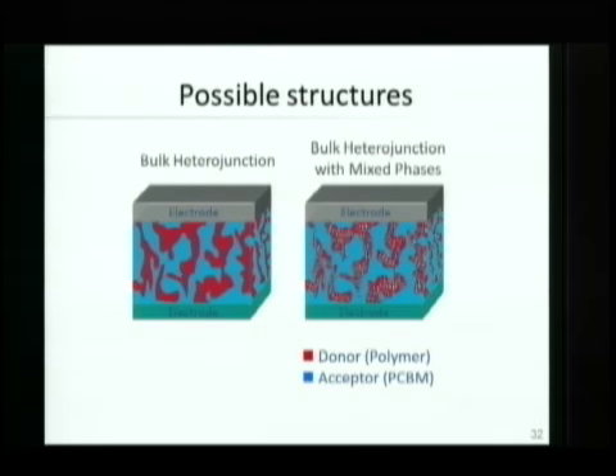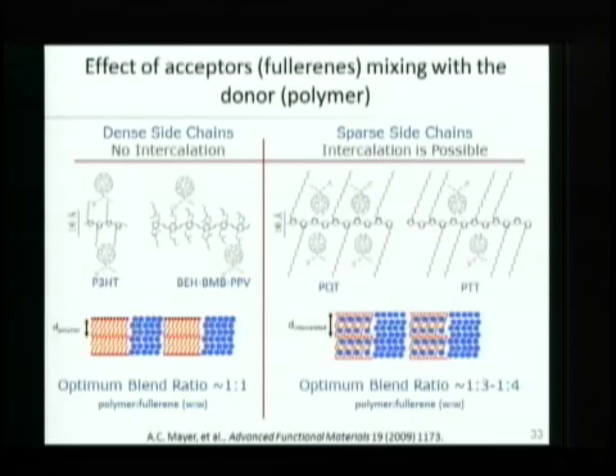And we need to know things like, do you have pure regions of donor and pure regions of acceptor, or do the acceptor molecules mix in with the donor region? And it turns out that if the acceptor is a fullerene, which is like a soccer ball made out of carbon, they can mix with the polymers that we use as donors. The polymers usually have insulating side chains on them, and we use that to make the polymers soluble so that we can put them in solvents and print them.